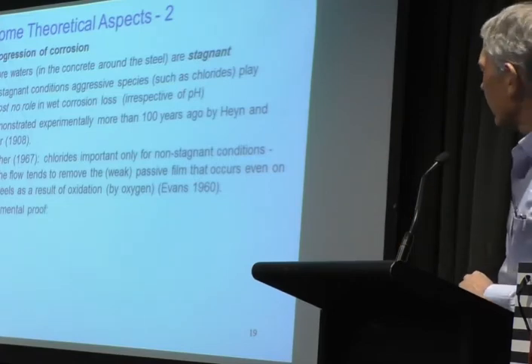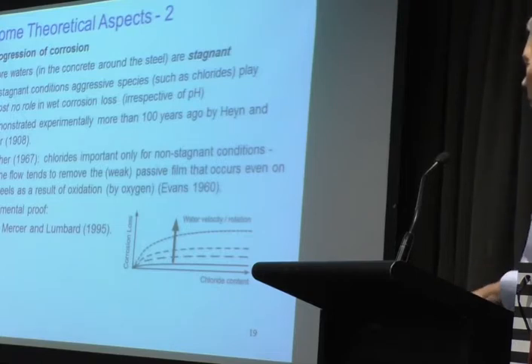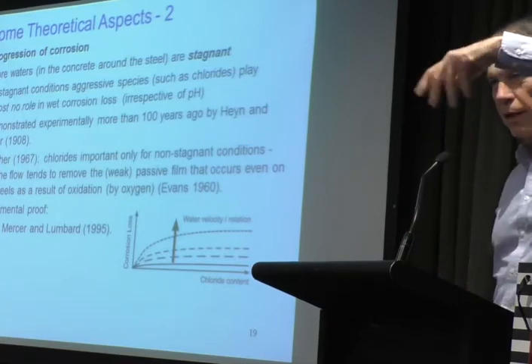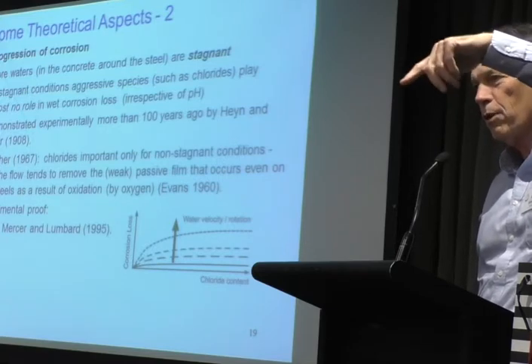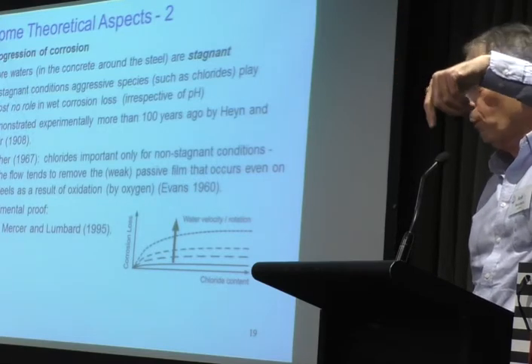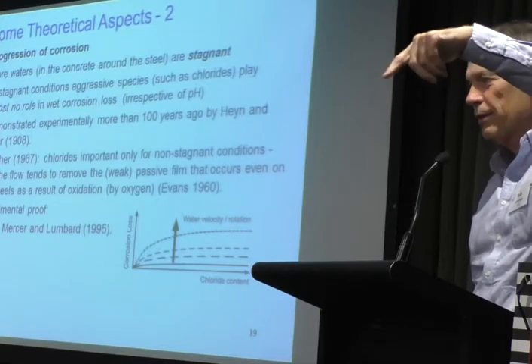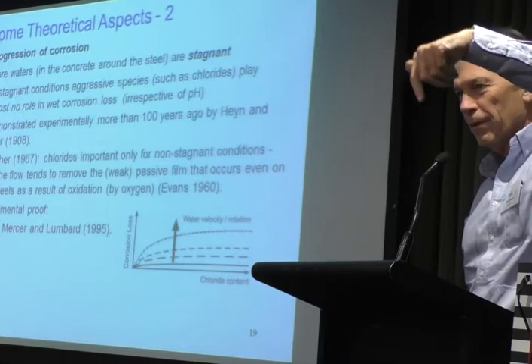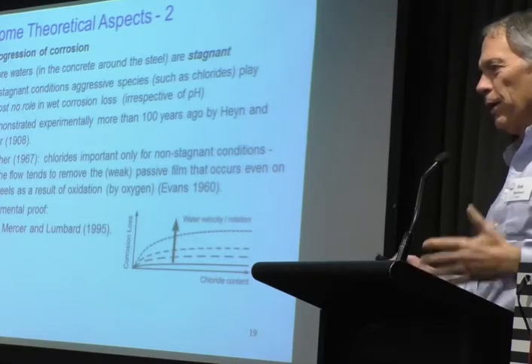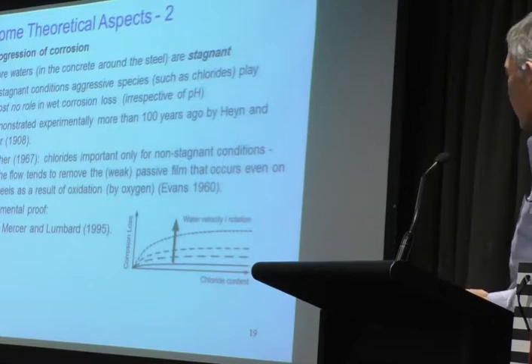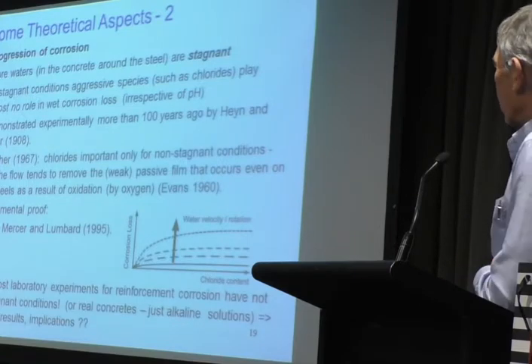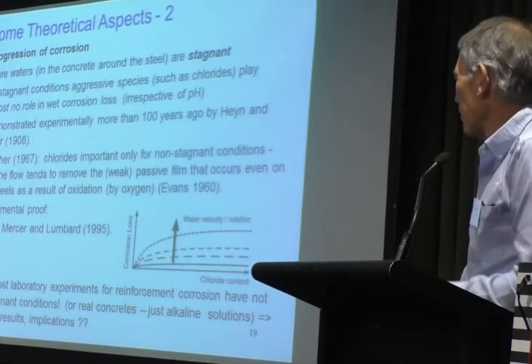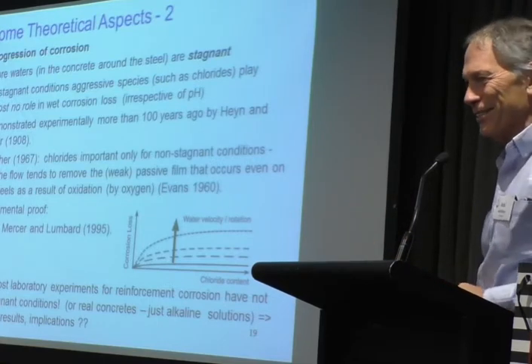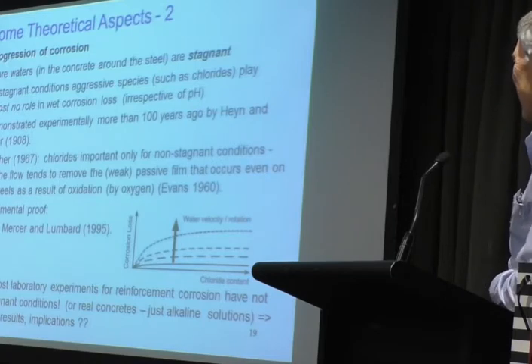And if you look at Mercer and Lumbard's, I think, a very nice paper published in the British Corrosion Journal before it changed its name, showed that very clearly, that if they used rotating electrodes so they could control it from zero rotation, it didn't matter what the chloride content was, nothing much happened. But as soon as they increased the angular rotation of the coupon, the amount of corrosion went up. So they were destroying, if you like, the oxide layer. So the stagnant conditions are really important. Now, as Warren has already mentioned to you, most laboratory experiments don't actually use stagnant conditions, right? So yeah, it's a bit of a problem.